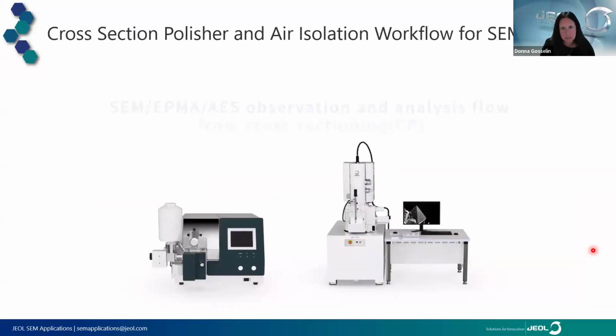So I'm going to show a little video here with a typical air isolation workflow, using our cross-section polisher to create a cross-section for SEM analysis. The benefit of using this cross-section polisher, which is a broad argon ion milling tool, is that it eliminates artifacts associated with traditional mechanical preparation. So pristine cross-sections can be made from difficult materials that are brittle, fragile, or multi-layer coatings that might have differences in thermal expansion. And it can also be equipped as a cooling cross-section polisher for cryogenic temperatures, which is beneficial for thermally sensitive samples that might otherwise degrade if you expose them to the argon ion beam.